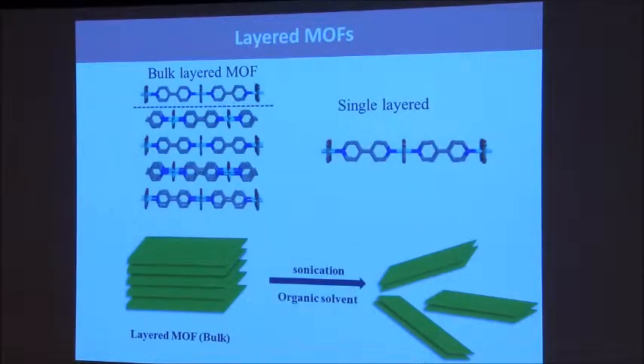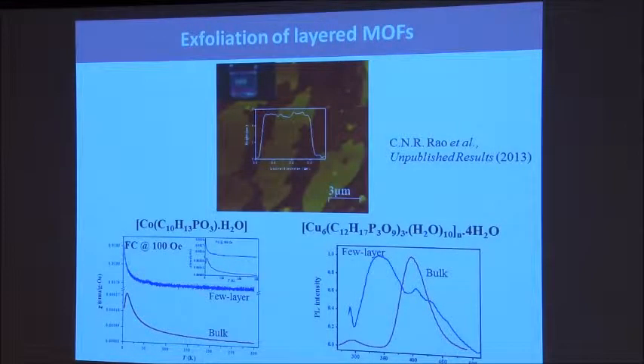Similarly, just like molybdenum sulfide, we have got metal organic frameworks, a lot of work going on probably even in Waterloo. Lots of inorganic chemists work on metal organic frameworks. Many of them have layered structures. I can remove one layer or two layers by either exfoliation or ultrasonication. And you see here is a material which you have grown. The bulk is giving a luminescence band here. As soon as you make one layer or a two layer, you see it shifts. A lot of properties of this kind have yet to be studied.